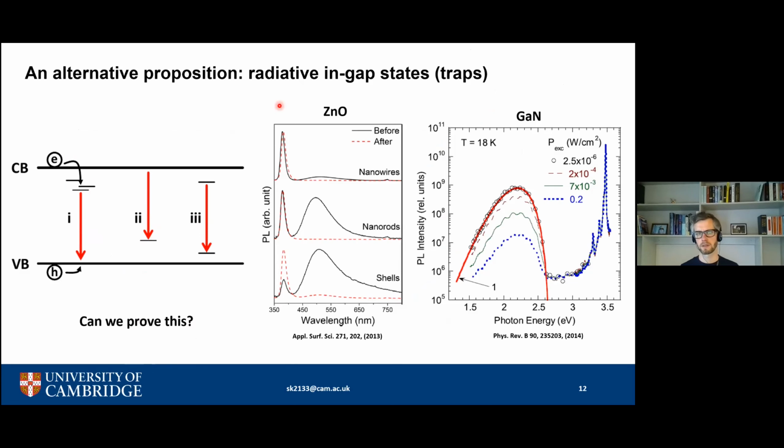And actually, if you look at the literature and compare comparable systems, for example, zinc oxide or gallium nitride, both form excitons, both are very polar lattices. There you see similar photoluminescence spectra, right? A narrow emission band and a broad emission band. And there everybody refers to some sort of defect state, either vacancy, interstitial, or an impurity. Nobody invokes a self-trapped exciton to explain it here.